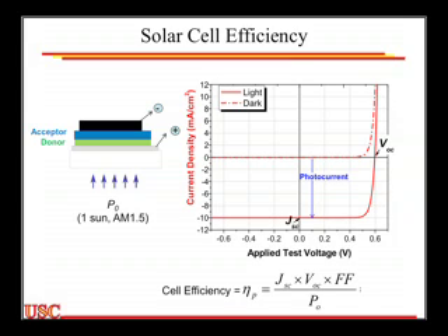The difference between the dark curve and the light curve is the photocurrent. And so JSC, or the short circuit current, is what you see at 0 applied bias. As you go to higher and higher bias, what we're doing is applying a voltage that opposes the voltage that we're making in the photovoltaic cell. So we're applying in the forward bias regime. Ultimately, we apply enough voltage to the device that we shut it off. And so at VOC, which is the open circuit voltage, that's when we've shut the device off.